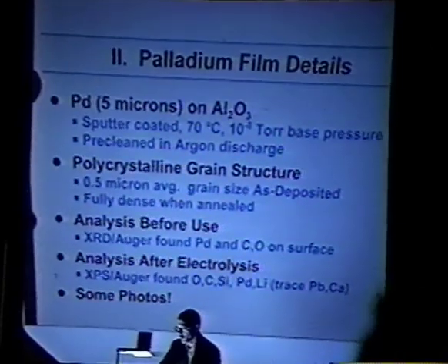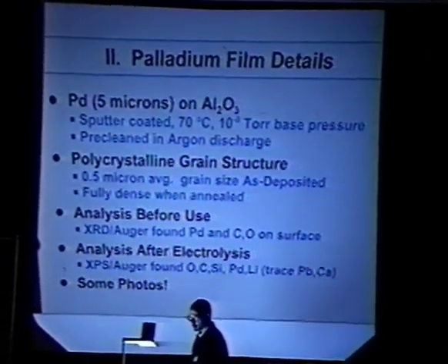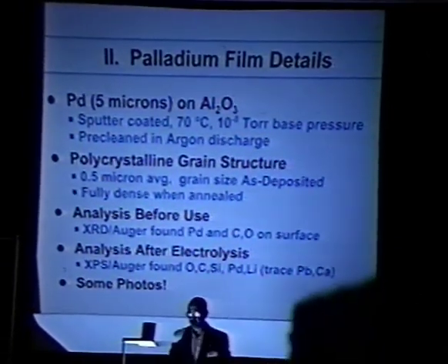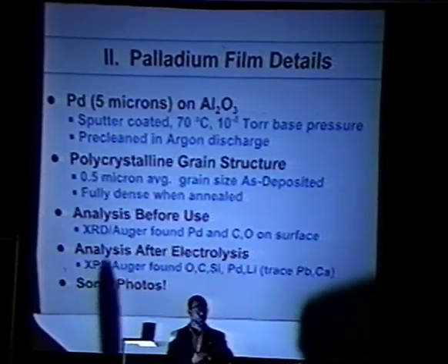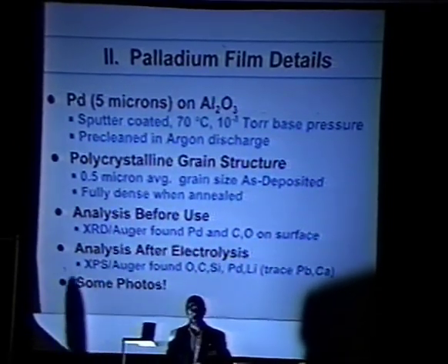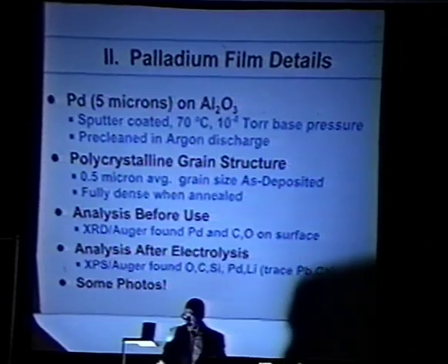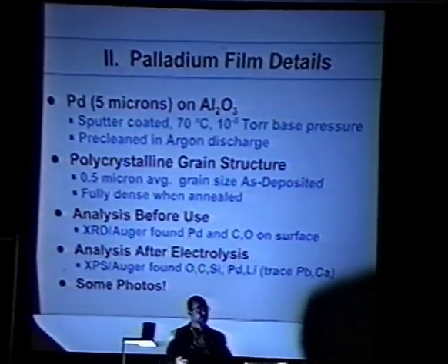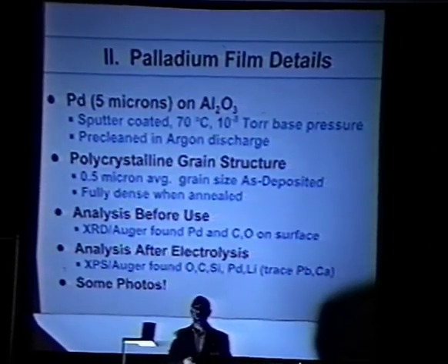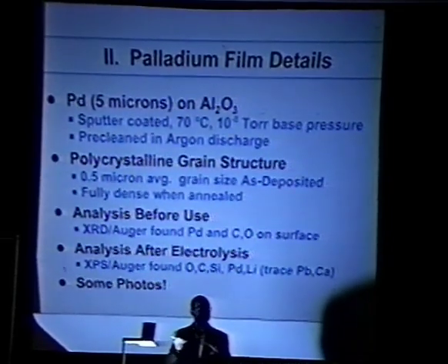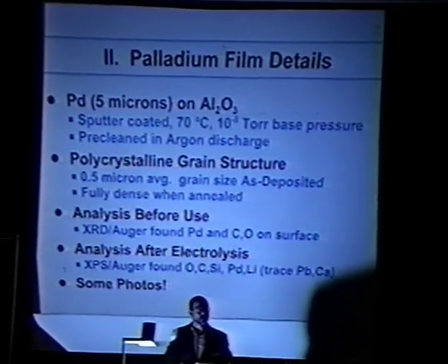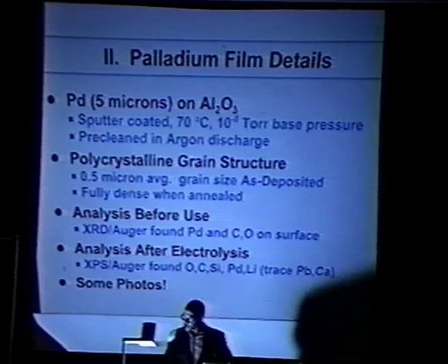Now, the palladium itself, I'm not going to focus too much on that today. There's quite a bit of detail, but essentially it's palladium, 5 microns thick on aluminum oxide. It was sputter coated by Mike Ridgely at the University of Alabama at 70 degrees centigrade deposition temperatures, which means these films, once the crystals start to grow, freeze real fast. So we end up with very small grain sizes.